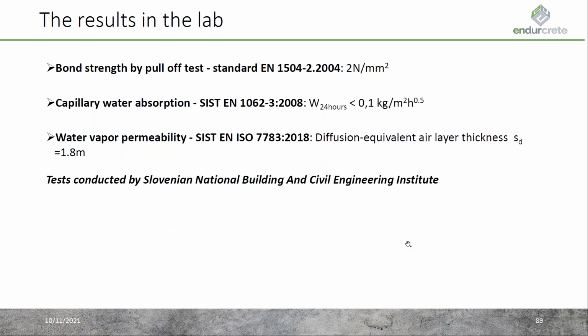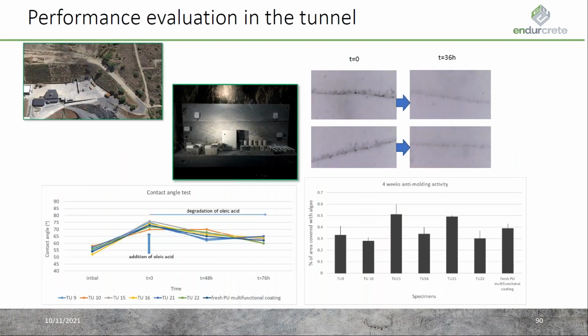Moreover, the Slovenian National Building and Civil Engineering Institute, ZAG, conducted bond strength, capillary water absorption, and water vapor permeability tests on the coatings that showed acceptable results in every case. And finally, the evaluation in real environment is ongoing at the moment.